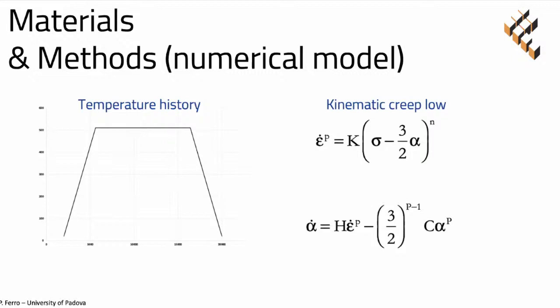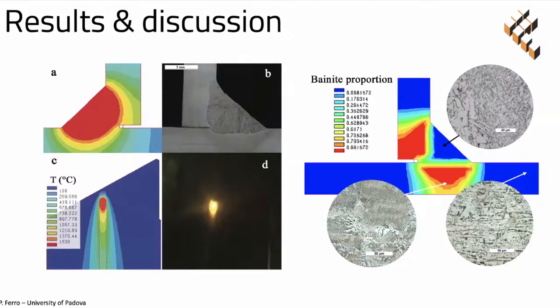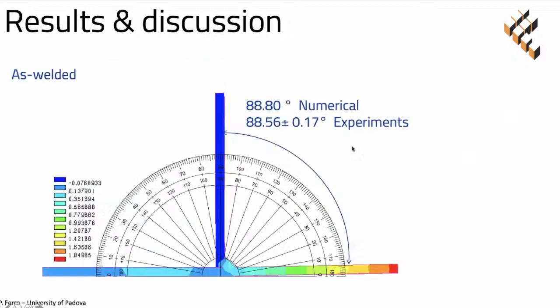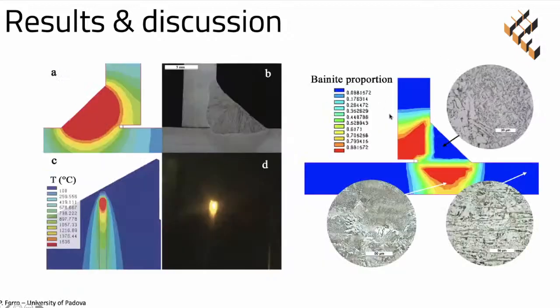These are the thermal results on your left, and you can see a comparison between the dimension and shape of the fusion zone calculated by numerical analysis and by experiments. And also the length of the tail of the fusion zone is compared with those obtained by experiment. And on the right side of this picture, you can see also the metallurgical result.